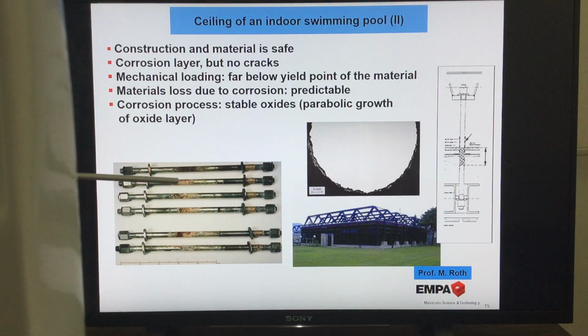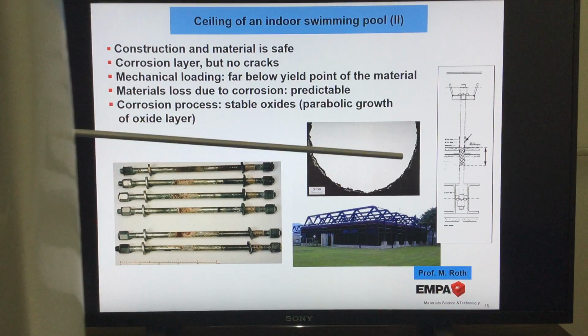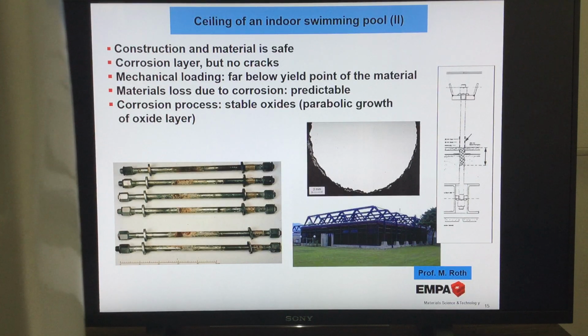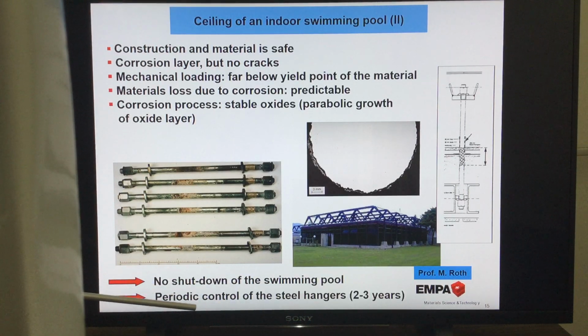But of course not those that had been replaced, rather those that had already been inside for about 12 plus 3 years, 15 years, and checked if this corrosion layer is stable, not growing. Then we are absolutely safe. So no shutdown of the swimming pool and periodic control of the steel hangers. So all these investigations and our knowledge about corrosion of steel, of this ferritic steel, were important to come to a clear conclusion.